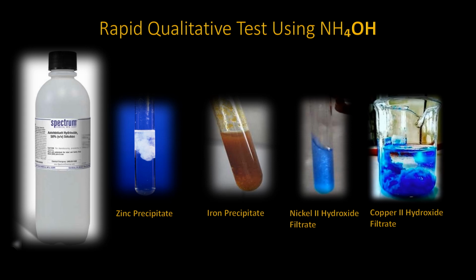If your filtrate turns blue, the indication is that there is a presence of copper or nickel, or both. If your precipitate turns white, your ore will contain zinc.